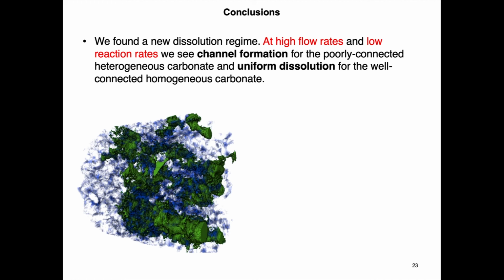The effective reaction rates in the channeling regime are up to 2 orders of magnitude smaller than that measured on flat substrates with no transport limitations, implying that transport of reactants and products in regions of the pore space away from channels is significantly impeded.